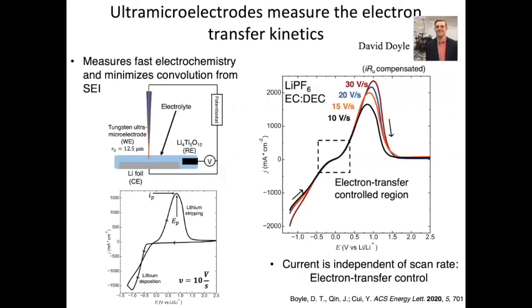So in order to understand that, we developed tools a few years back using this microelectrode, shown on the top left right here. It has a radius of about 12 micron, so it exposes very small areas.